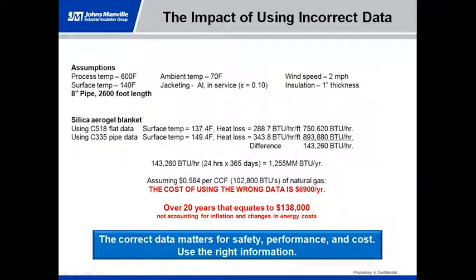And if you look down at the product that was used, if you would have selected the C518 data in the 3E Plus software, versus C335, you would have had a 12-degree temperature difference, which would have put you from a below 140-degree safe-to-touch temperature to 150, which means you would burn within a second after touching that hot surface. There's also a 55 BTU per hour per foot difference, which doesn't sound like a lot, but